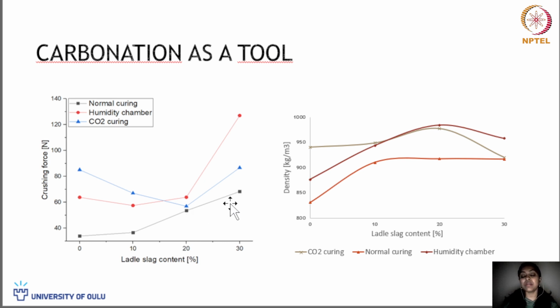And the crushing force decreased up to 20% and then increased at 30%, maybe because of the particle packing efficiency. It is also studied in several cases that if you add particles of different size in the right proportion, without even any reactivity of this material, the filler effect will also give you some positive impact on the strength improvement of these materials.